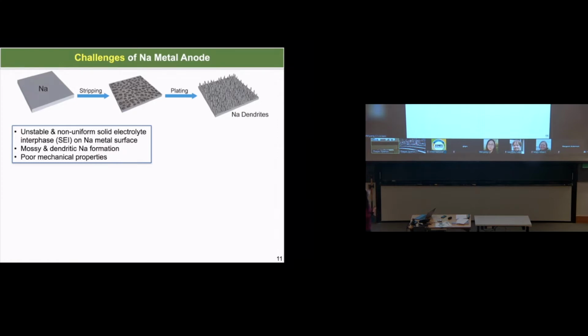And this unstable SEI formed on the anode surface will cause different issues. For example, what we call mossy and dendritic sodium formation, and another thing is that because sodium is very soft, it has a much more severe mechanical property issue, because if you press it, it can deform during the battery assembling process.